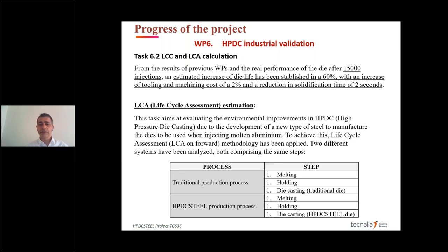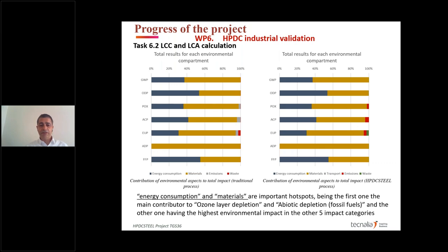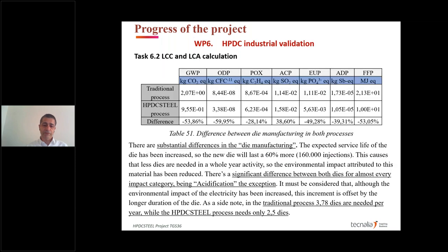We have seen that there has been an increase in machining cost for the die of about 2%, but there has also been a decrease of 2 seconds in the cycle time of the process, because there has been an increase in the thermal conductivity of the steel by the addition of the carbides, and we have decreased the solidification time in the die. So the life cycle estimation, again, the same process, the energy consumption of materials is very similar, so we will go quickly with that.